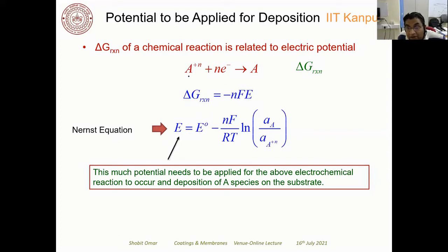So you see there is an electrochemical reduction occurring at the cathode side, given by this reaction. If delta G is the Gibbs energy change of this particular electrochemical reaction, then it is related to the electrode potential by delta G equals minus nFE. Now this E is dependent on the activity of A and the activity of these ions, so the concentration and temperature will dictate what the electrode potential is.